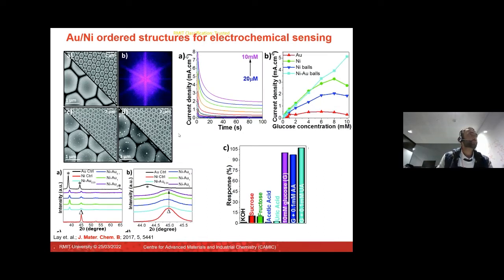to undergo glucose sensing. The reason we've used gold and nickel is because they overlap at the same voltage when you're trying to do chronoamperometric glucose sensing for diabetic applications. Okay, so we've got a nickel substrate colloidal structure, and we've galvanic replaced gold on that.